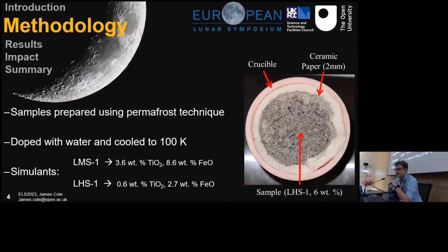So to the experiments themselves, I've prepared samples using what's known as the permafrost technique. You add water to a lunar simulant, you let it diffuse through, and then you cool it down to 100 Kelvin. I used water contents between 3 and 12 or 15 weight%. Basically, I went up to the saturation point of the simulant I was using. And there's a few reasons for this. The main one is that these PSRs aren't going to be a consistent water content throughout them. So I wanted to check, how does the microwave heating get affected by different water contents? Is it better suited to certain regions of PSRs?